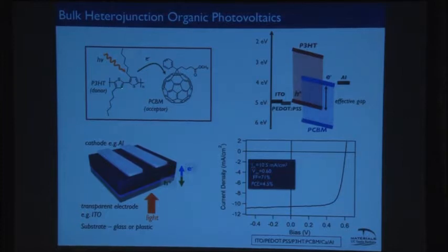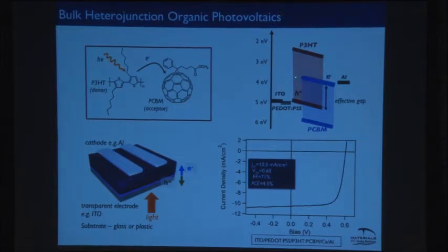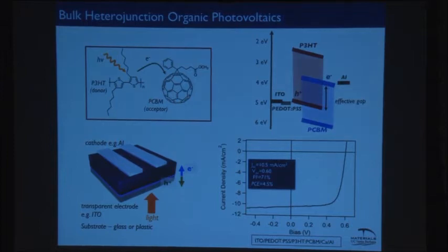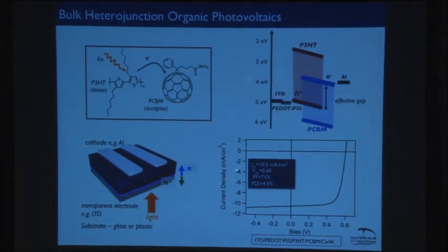They have an electrode on the top, like aluminum, that has a lower work function that's lined up with the fullerene. The idea is that you shine light on the material, and the polymer is the stronger absorber. The light is absorbed here, and you get an electron transfer event. The hole stays in the polymer. The electron stays in the fullerene. Schematically showing the energy levels here, the hole moves in this, the electron moves in that. They're all mixed together. You collect them at the electrodes, electrons to the top in this case, and holes to the bottom. And you get reasonable solar cells. This is a 4.5% efficient P3HT PCBM solar cell. Why do you use fullerenes? It turns out this electron transfer process is ultra fast, so that's good.